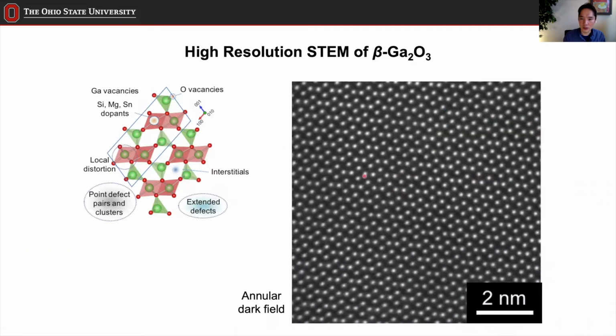All right, so now if we apply this technique to look at the gallium oxide structure, then you get something like this. This is the same mode that I just explained, and using the annular dark field mode, you get an image like this. In this case, because the gallium atoms are heavier than the oxygen atoms, mostly you see the intensity from the gallium positions, right? So all these positions are gallium positions, and the length scale is 2 nanometers here.